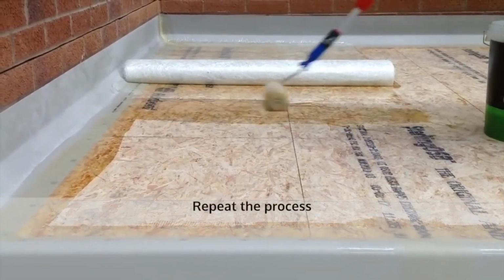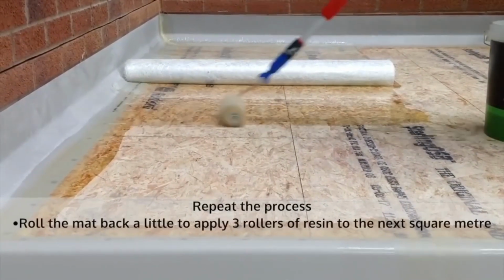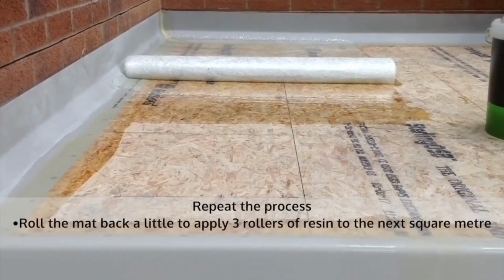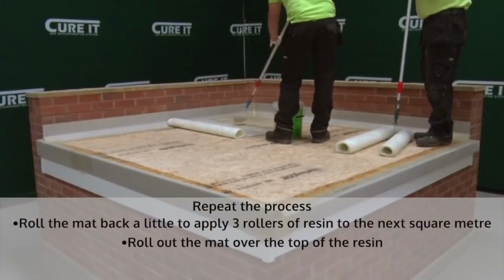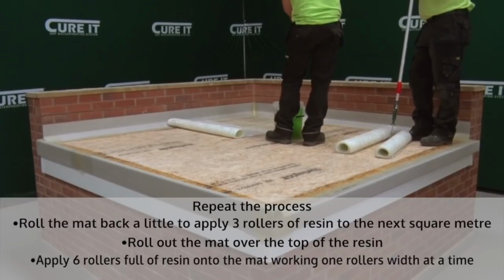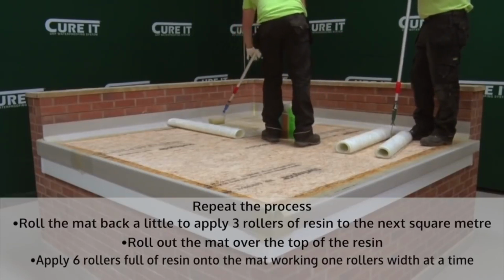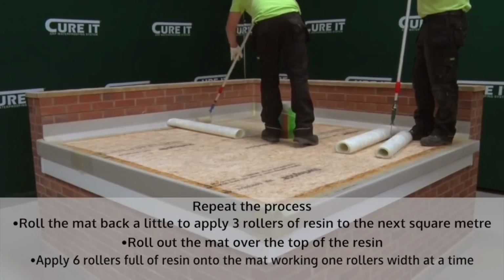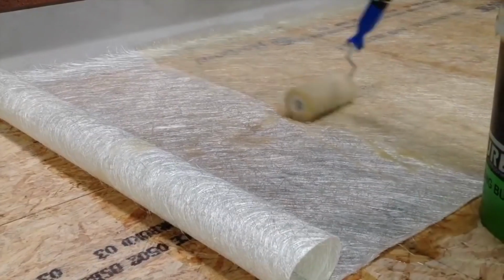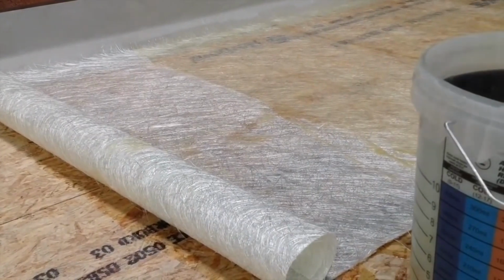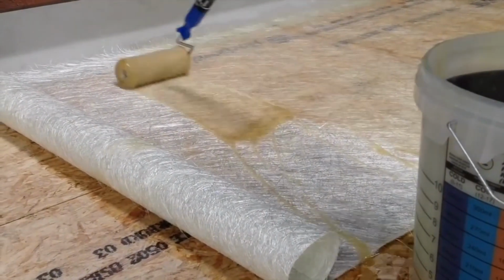Move on to the next square meter of decking and repeat the process, applying the resin to the deck, covering with reinforcement mat and applying 6 rollers of resin on top of the reinforcement mat. Check for dry areas and pinholes as you go. Pinholes in the laminate will lead to porosity and water penetration. If in doubt, apply a little more resin.